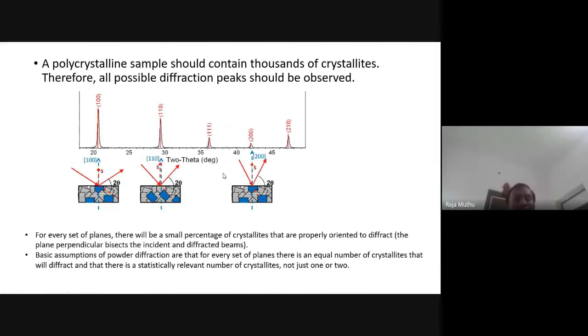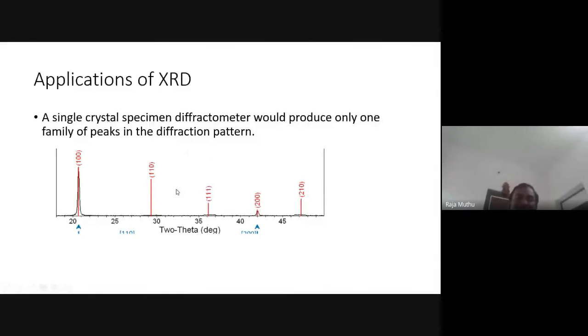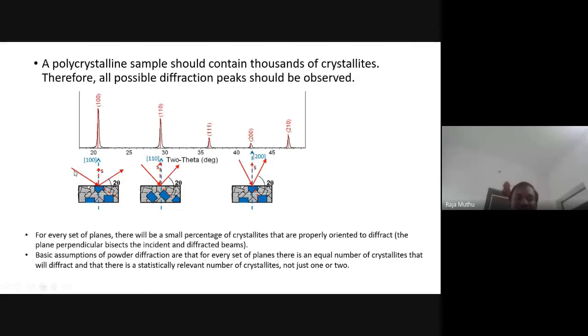A polycrystalline sample should contain thousands of crystallites, therefore all possible diffraction peaks should be observed. For a single crystal there is no issue, it is only one unique pattern. But for a polycrystalline sample, all possible angles have to be taken. For every set of planes, there will be a small percentage of crystallites that are properly oriented to diffract. The basic assumptions of powder diffraction are that for every set of planes there is an equal number of crystallites that will diffract, and there is a statistically relevant number of crystallites, not just one or two. That's why it is supposed to be a random distribution, so that an equal number of crystallites diffract in all cases.